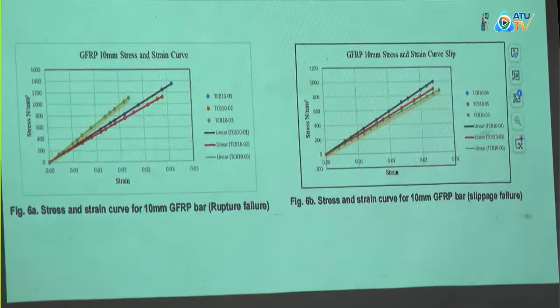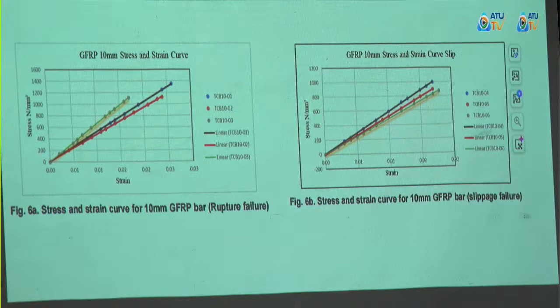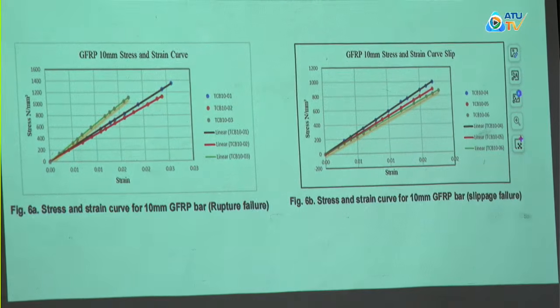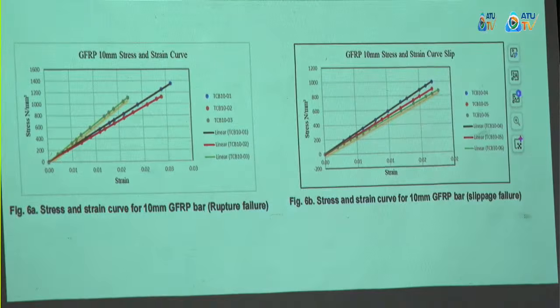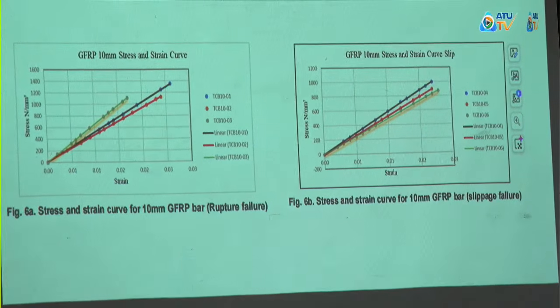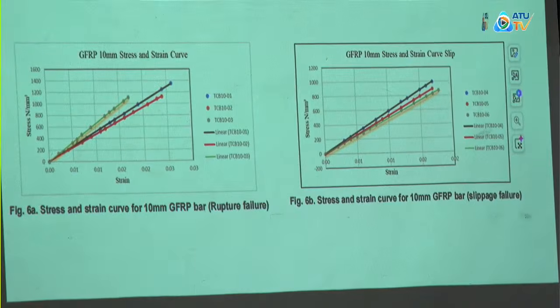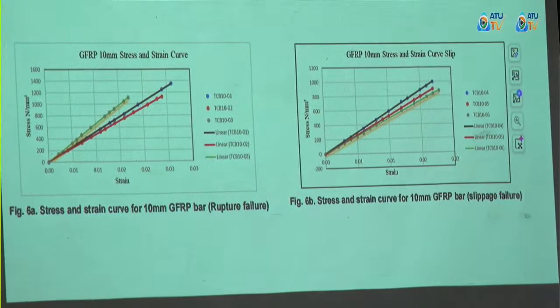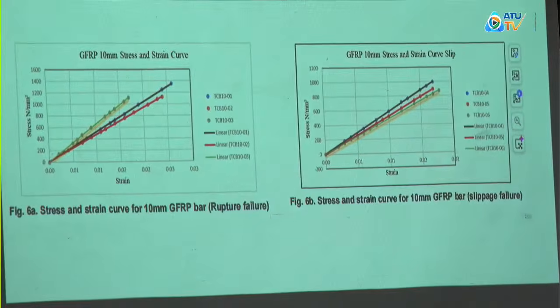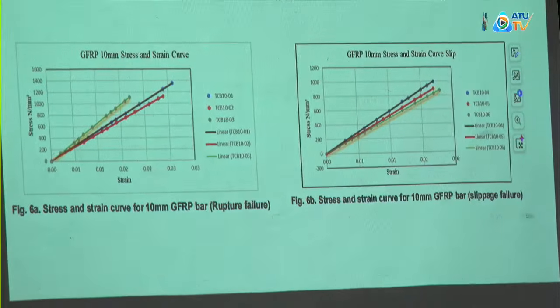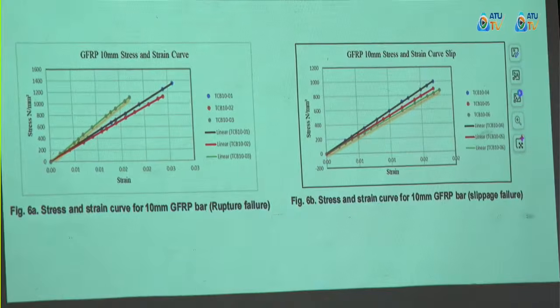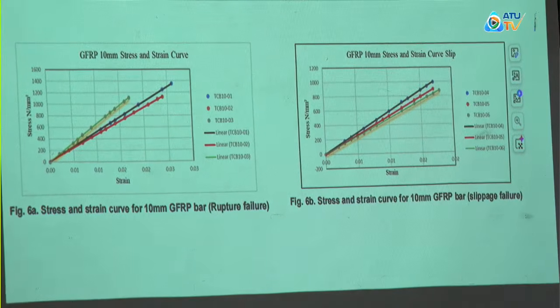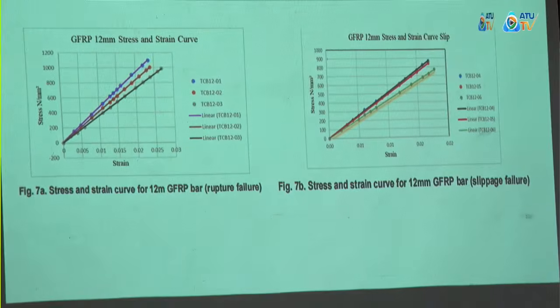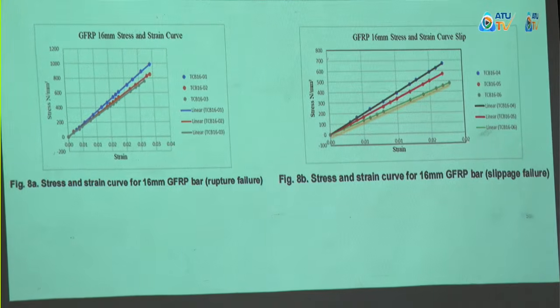Next one. Okay, here we have the stress strain curves of the GFRP bars. The researcher realized, as earlier cited by Professor Kankam, that the GFRP bars are linearly elastic. So you have the stress strain curve for the 10 mm when the GFRP ruptured, and the stress strain curve for the 10 mm bar when there was slippage failure. In both cases, you see that the GFRP bar is linearly elastic. The same applies for the 12 and the 16.